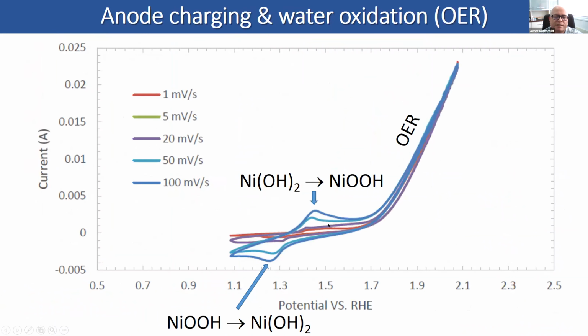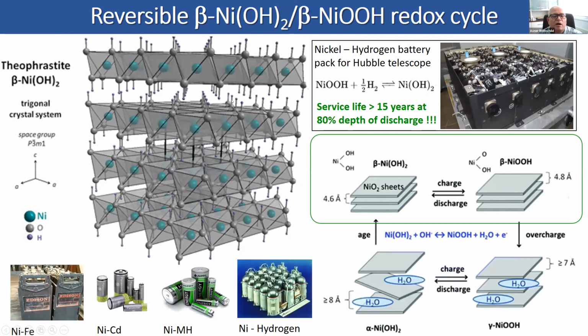So to show you now in real results, this is the charging reaction that we do in the first step. So we charge nickel hydroxide to oxyhydroxide, and you can see that we do this at a lower potential than the potential where we can evolve oxygen, and that is essentially the energy we save. Yes. So about the reversibility of this reaction, we do convert this beta nickel hydroxide, which is the layer structure, where in these interlayer spaces, you have hydrogen pointing out of every oxygen atom. That's the nickel hydroxide. And in the nickel oxyhydroxide, we extract half of this hydrogen out of the system. So that is a reversible reaction that consumes half of these protons, go out and combine with the hydroxide ion at the surface of the electrode to produce water.